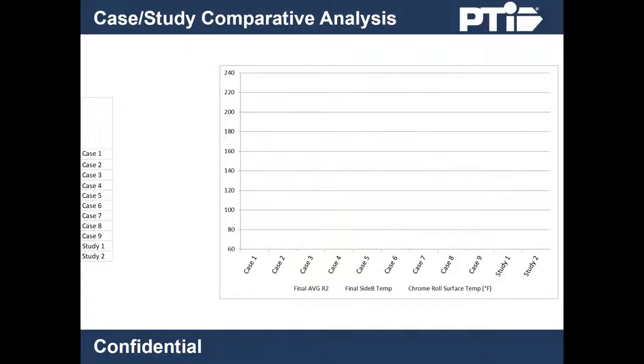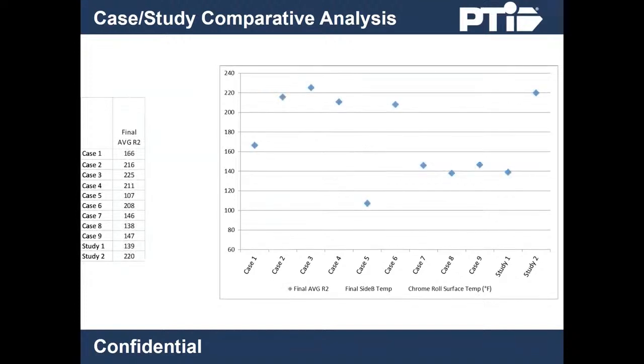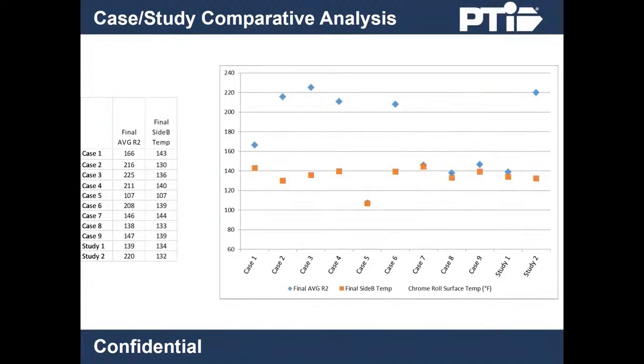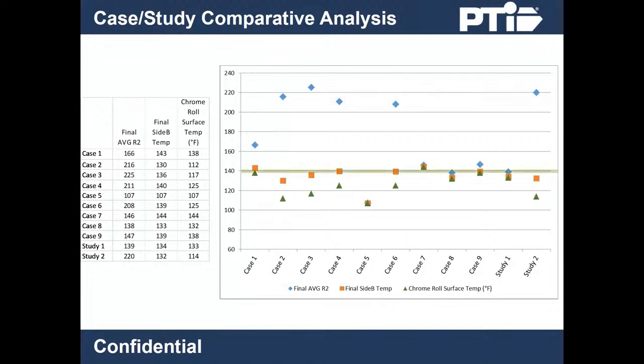We just looked at a lot of data, so let's do a quick summary analysis of some important thermals. The final average temperatures are widely varied, but the final side B temperatures appear to coalesce. The chrome roll temperatures are varied, but they appear to max out at about 140 degrees. If you recall, we identified 140 degrees earlier in this presentation as the maximum roll sheet surface PLA release temperature.